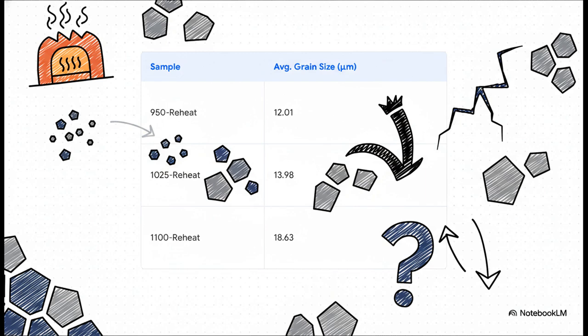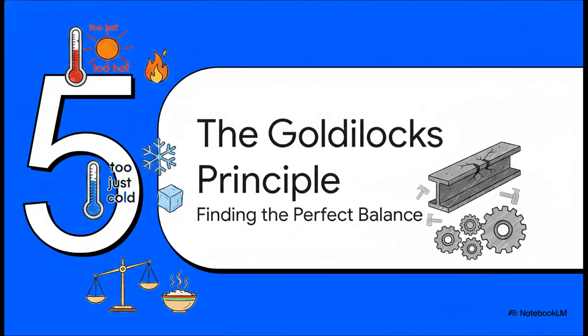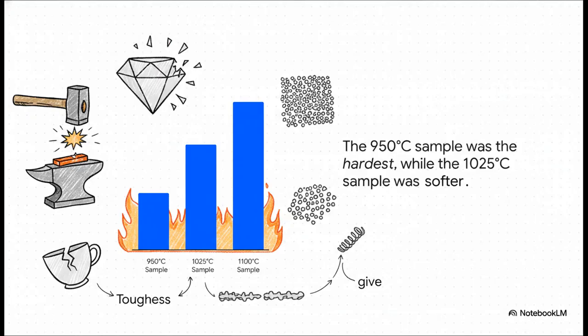So this kind of flies in the face of that simple smaller is better rule. What is really going on here? Well, it turns out that toughness isn't just about one single property. It's a really delicate balancing act. It's like the story of Goldilocks, right? You don't want things too hot or too cold, too hard or too soft. You want them just right. And there was another piece to this puzzle. And here it is. Hardness. See, that 950-degree sample with its superfine grains was also the hardest material of the three.